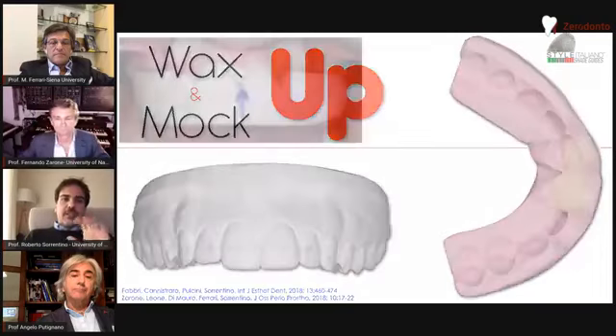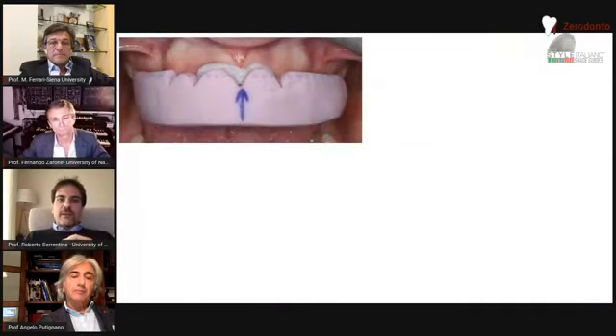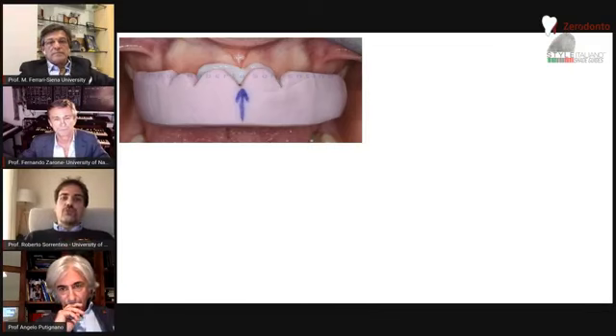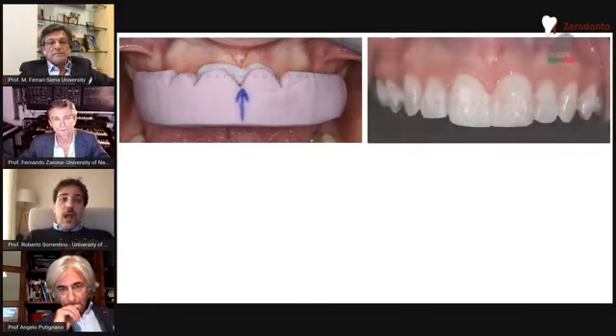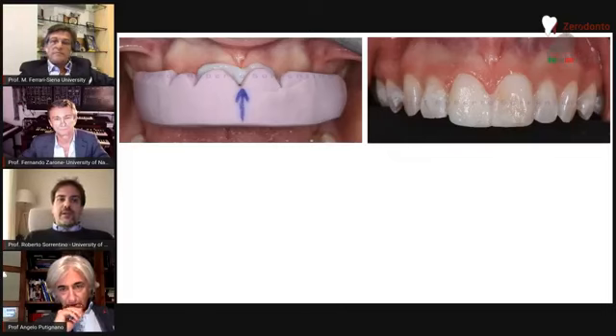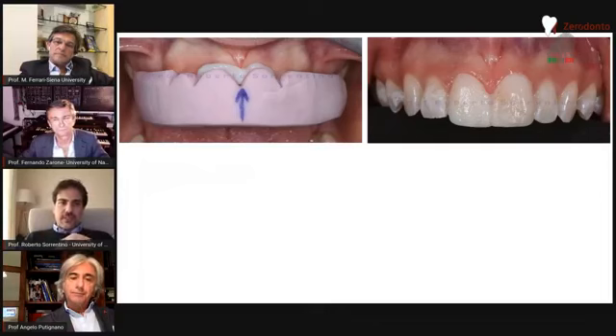And the proper ditching of the model at gingival level and the scalloped shape of the silicone template allow resin to flow away and clean it up very easily. I always mark a reference point on the midline in order not to strain the resin material. I prefer to use self-curing bisacrylic resins because of their precision, hardness, and polishability.